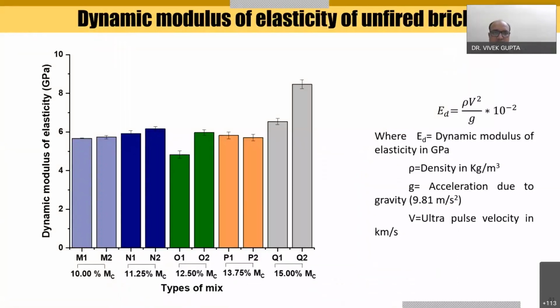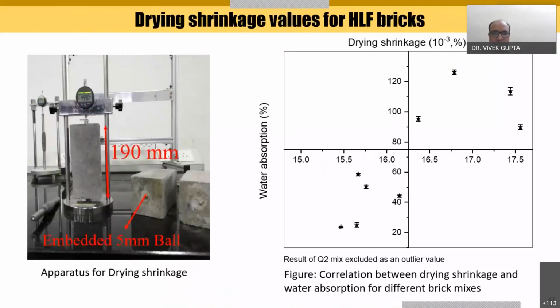Then we have observed a similar trend for the dynamic modulus of elasticity, and these are the results of drying shrinkage, where we found that the drying shrinkage of the bricks is closely related to the water absorption characteristics of the bricks. With low water absorption we found low drying shrinkage, and with high water absorption we found high drying shrinkage.